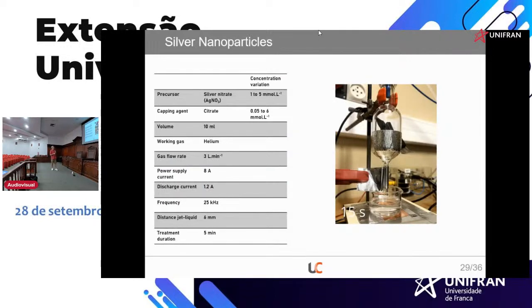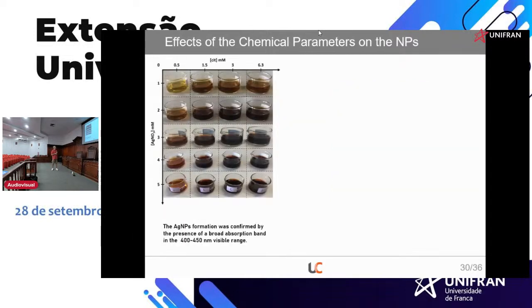So here, it's working. Here it's a function of time. You see the plasma in the beaker. We produce some silver nanoparticles. The conditions are with a capping agent, citrate, and some experimental conditions.